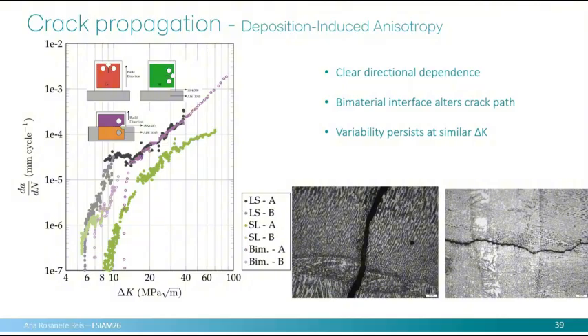So the main conclusion, you have all the results here. Of course, the crack propagation is totally dependent on the building direction, so it is direction dependent. For example, the base material has influence. We also did some base material samples where we could understand the influence of the base material. So it also alters the crack path, but also the scatter of all the results, as you can see.